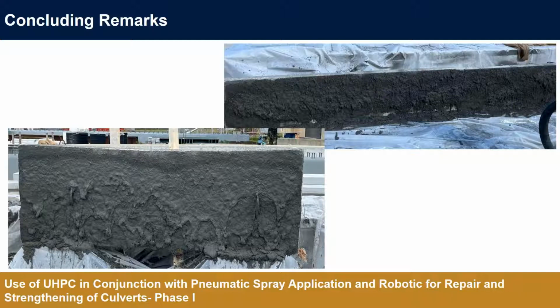Thank you very much. Let me see another question. Asking, can you explain a little more about the mix for the pneumatic spray? Yeah, the base mix is published under ABC UTC, which is the ABC UTC mix. But what we did is we changed the rheology to make it less flowable by reducing the water cementitious ratio, so we played to reduce the flowability in order to build up the thickness. For more details you can access our website for the ABC UTC UHPC mix.